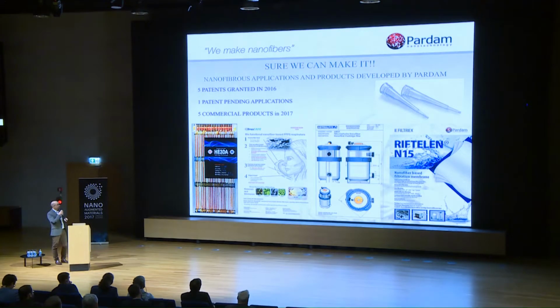And the last, in the corner, you don't see it, but at the tip of the analytical tips, there are nanofibers, ceramic nanofibers, which are used for sorption of special peptides within the analytical work. So, thanks to the high surface area, we can use the fibers as sorbents.